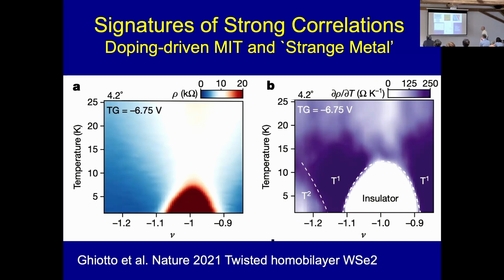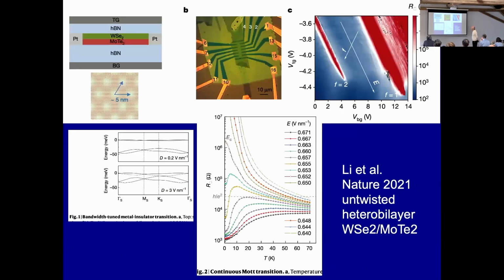In this experiment, which is the Cornell experiment on heterobilayer moiré, again, resistivity versus temperature was measured, and you see something that looks extremely similar to all the curves I've shown you before, displaying a very nice metal to insulator behavior. And as Jose mentioned, the first thing that the experimentalists are going to try is to scale this data. And they managed to scale the data quite beautifully, as you will see.